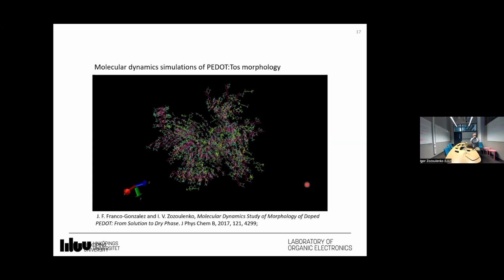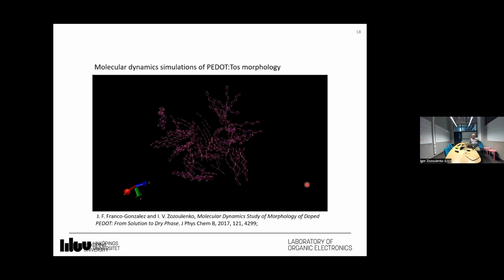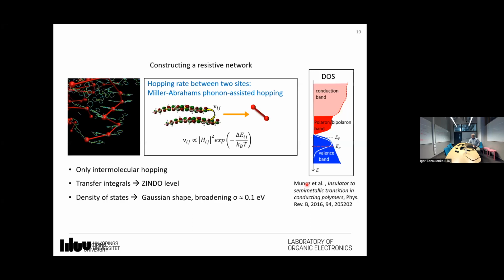Okay, and then if I go more slowly, step by step. First, as I said, these are calculations of the PEDOT film morphology. This plot shows only the backbone of the polymers. I removed the counterions, so only backbones are shown, because the backbones are where the electron transport takes place. Then, each chain we consider a so-called transport unit. We basically ignore intrachain motion because chains in PEDOT are very short. So it's only interchain hopping which is important.